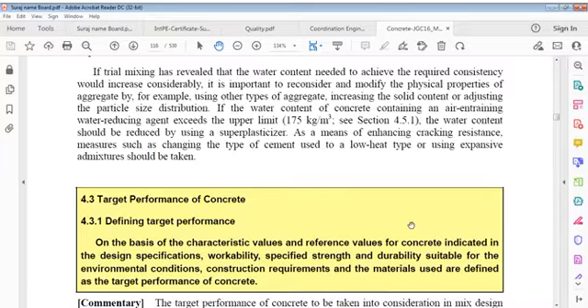If the water content of concrete containing an air-entraining and water reducing agent exceeds the upper limit of 175 kg per cubic meter, the water content should be reduced by using a superplasticizer as a means of enhancing cracking resistance. Measures such as changing the type of cement used to a low heat type or using expansive admixtures should be taken. We have here a very important part of this specification, and that's trial mixing.